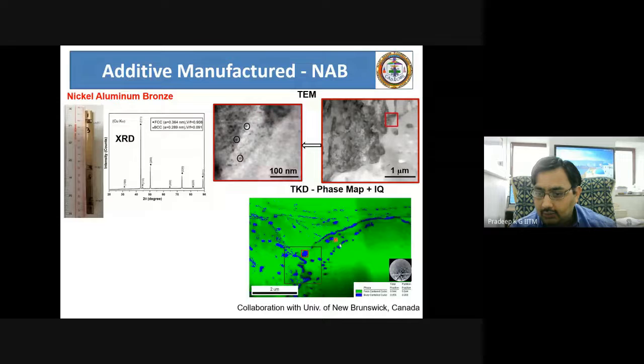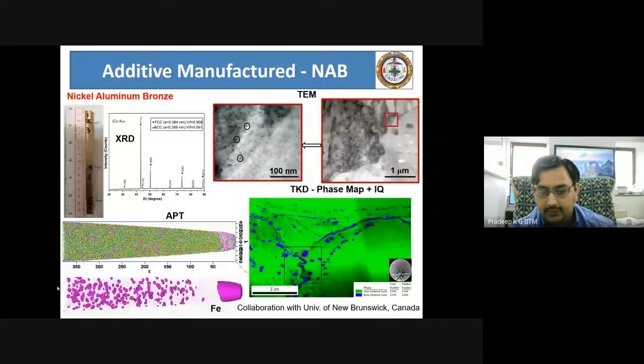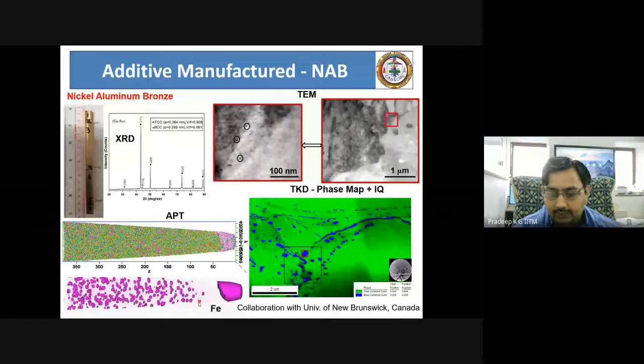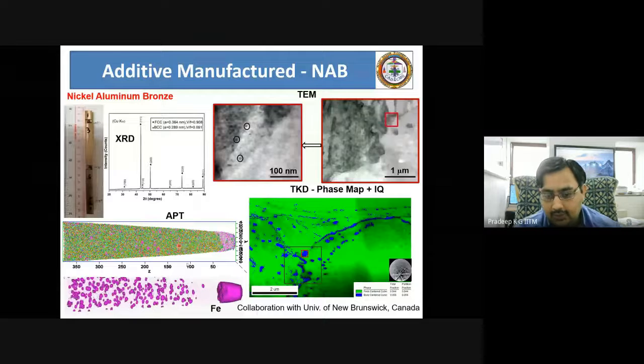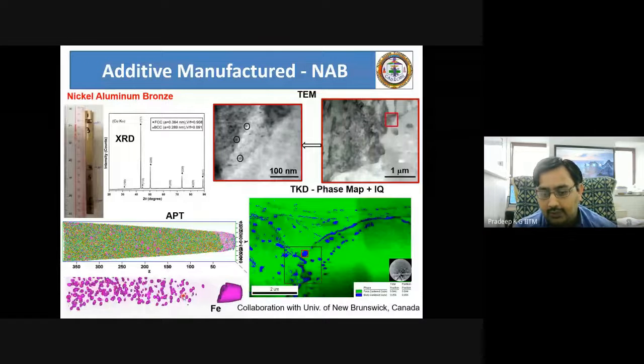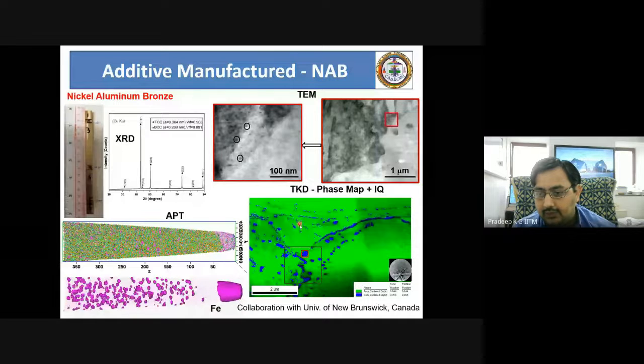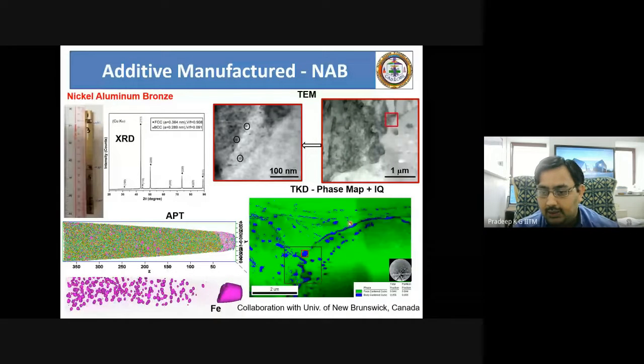So if you now want to know precise morphology of the precipitate and their chemical constitution, you can take these nanoscale precipitates to the atom probe, and you can see now only the iron atom shown here, but all the atoms are shown in the top. Iron atom forms 2 different morphology, tiny little nanometer scale particles, which are those little ones that you see here. And you know these are all body-centered cubic structure, and this is now giving us an iron-rich precipitate information.